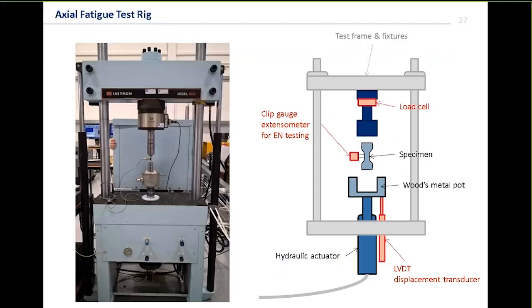Again, if you were to look at a typical rig, it looks something like this. The thing that dominates the rig that you notice first of all is the test frame around it. You'll also notice that we have a hydraulic actuator that applies the load. On this one, the hydraulic actuator is at the bottom, but it could quite as easily be a top-loaded rig as well. The specimen goes in the middle, and at the end we have a reaction. If we look at the sensors on the typical test rig, there is first of all a load cell. This is measuring the load that goes through the specimen. We have an LVDT, a linear variable displacement transducer. It's measuring the displacement that's applied to the specimen. And in this case, we also have a clip gauge, an extensometer or strain gauge, if you like, that's measuring the strain that's going into the specimen at the critical section.